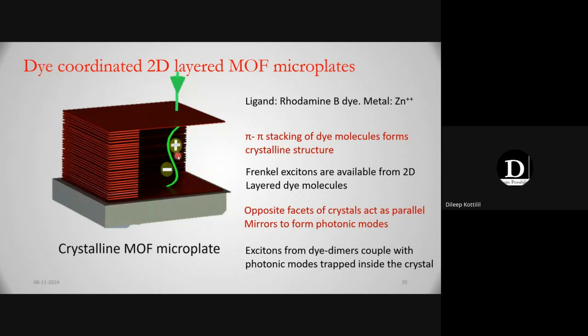So there are thousands or maybe millions of molecules available for the formation of polaritons. So the Rabi splitting can be very high, although the quality factor pulls down the Rabi splitting. The value of N, since it is very large, it dominates. So that is why we got polaritons in our system.